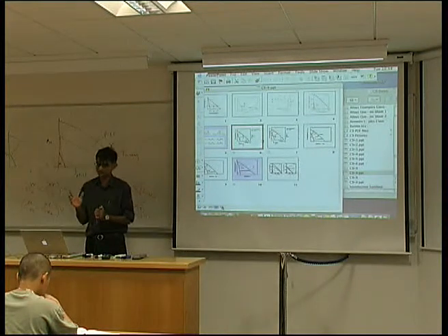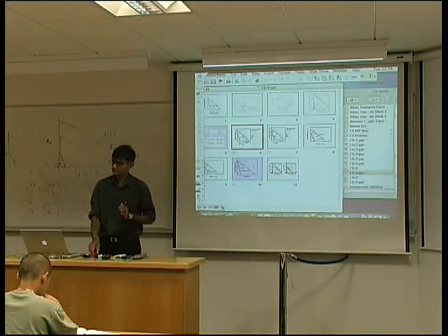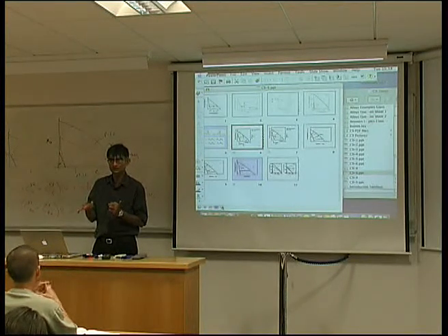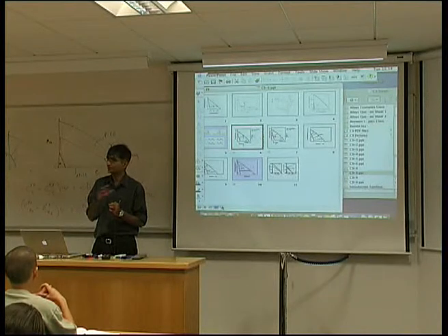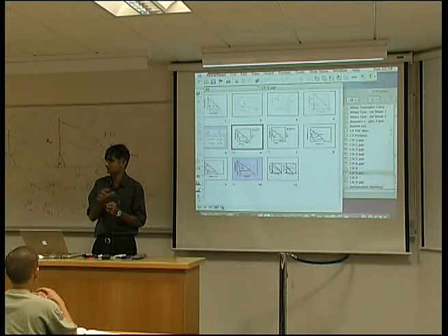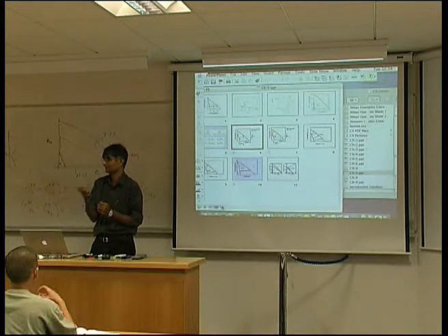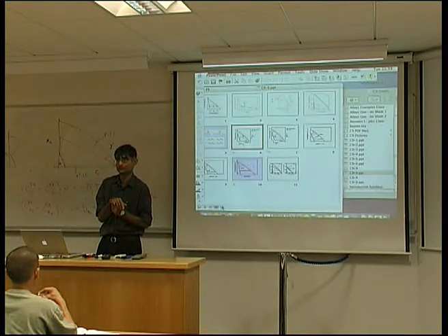So effectively, it becomes like a binary system. And the vast majority of steels, because we try to produce very fine grain structures, we transform them at a low temperature. And the para-equilibrium phase diagram would apply there rather than equilibrium, which makes life very simple, you know, because it becomes effectively like a binary phase diagram.